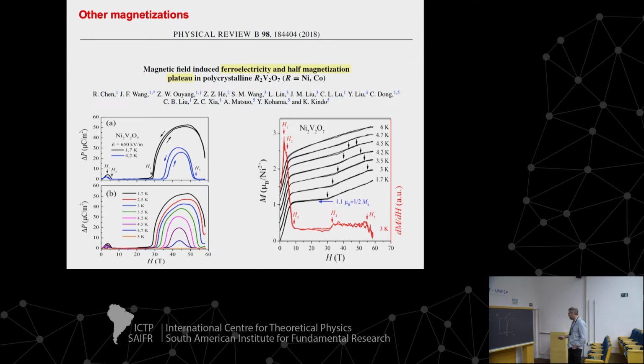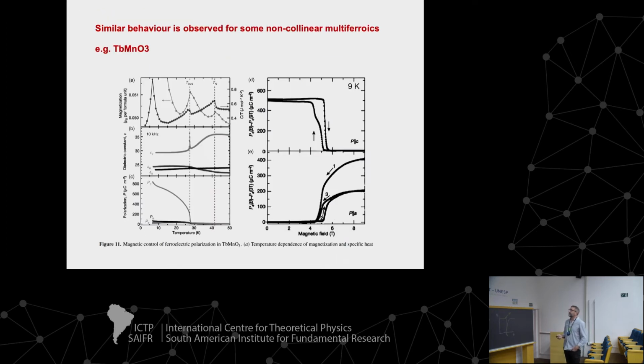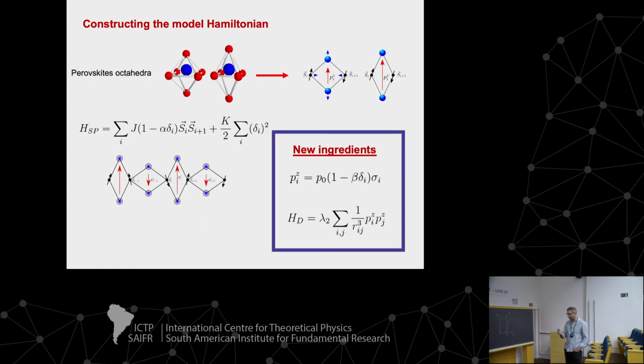So it's a kind of similar situation like here. Here you have a big change when you go out of the plateau, but nothing changes within it. And here it is the same situation, but in a higher magnetized state. Okay, and there are other cases too. This feature is also observed in some non-collinear multiferroics. So for example, in this terbium manganite, you see a big drop-off of P at the same place where, well, I don't have the magnetization curve here, I think. But the same thing happened with the magnetization, just to say that maybe there is something deeper behind.